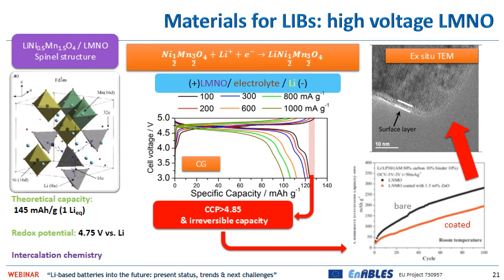The first one is the foreseeing of high voltage cathode materials. If we improve the voltage of the operating positive electrode, we increase the net energy of a full cell. One option is this lithium manganese nickel oxide that is a spinel structure and operates at around 4.8 volts versus lithium, that is more than 1 volt above the state-of-the-art lithium cobalt oxide. This material operates through an intercalation chemistry reaction and is able to exchange one full equivalent of lithium.